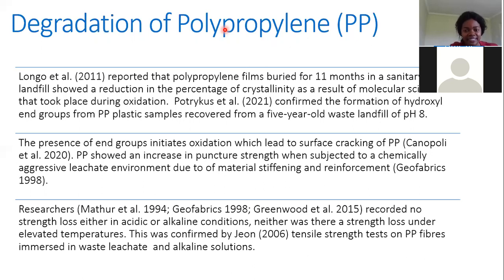So if the tie molecules that bond this crystalline and the amorphous region are broken, the strength of the polymer eventually reduces, and the structure of the polymer will also change. So researchers have shown that the percentage of crystallinity decreased when they collected polypropylene films that have been buried in some landfills, and this showed that oxidation took place.